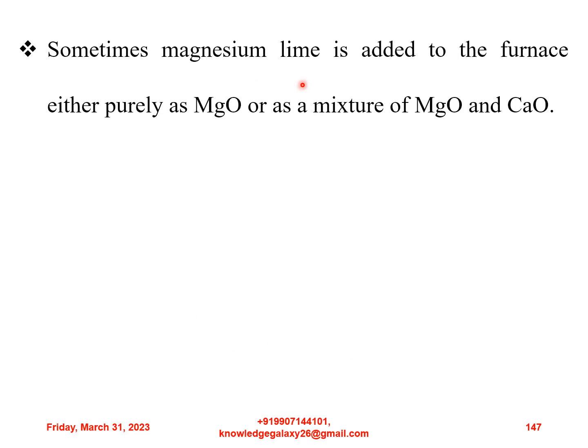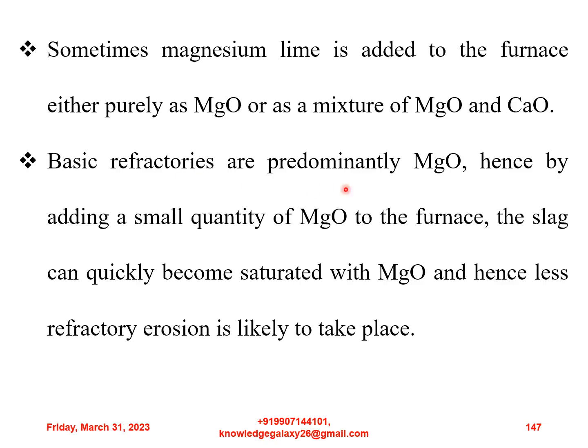Sometimes magnesium lime is added to the furnace either purely as MgO or as a mixture of MgO and CaO. Basic refractories are predominantly MgO, hence by adding a small quantity of MgO to the furnace, the slag can quickly become saturated with MgO and hence less refractory erosion is likely to take place.